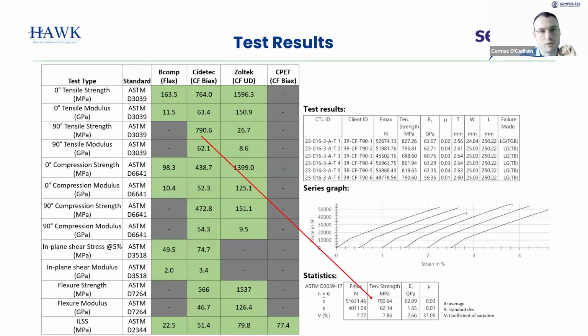These are the averages for each material. We looked at tensile strength, compressive strength, shear strength, and modulus for each of these as well, flexural and interlaminar. So these are the average of each batch of tests. So there's the table of the test results here. So for example, this one, 6 individual tests. We have our stress strain curves, and your average is here, so 790 in that case for that material.